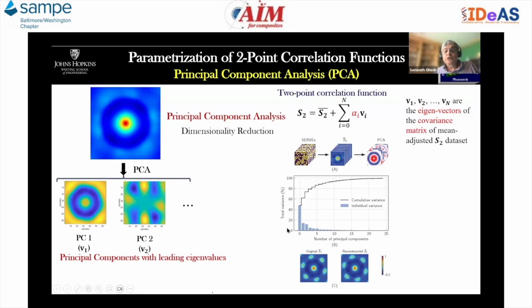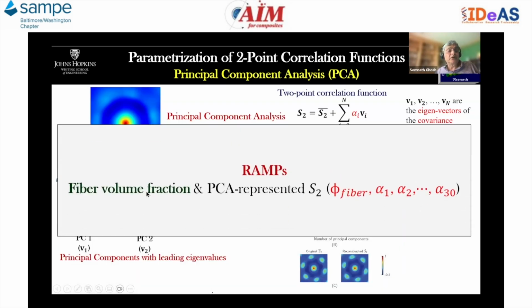As you can see here, the total variance decreases with the increasing number of principal components. After that, the higher order PCAs don't participate much in representing the variance. Therefore, we truncate after a certain number of principal components. But together with this, we also have an uncertainty quantification to see the effect of this truncation on the overall behavior. You can see this corresponds to the original S2 function, and this is the reconstruction using the PCAs. So the RAMPs here correspond to the fiber volume fraction as well as the PCA represented S2. These are the alphas.